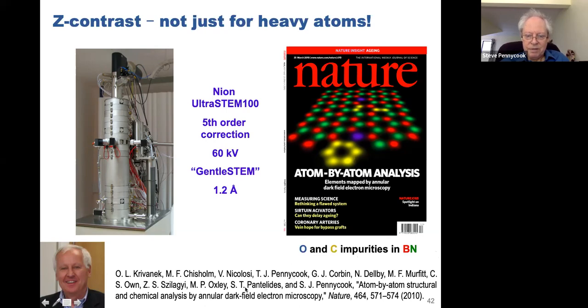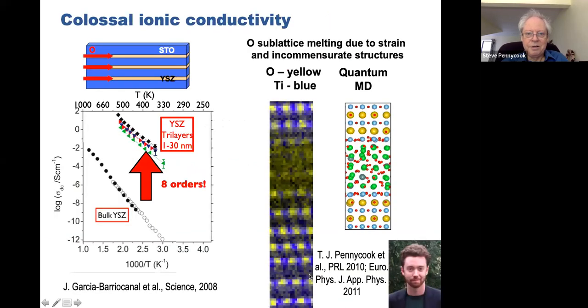And actually the guy who did this, at the same time, I said Sok Pantelides liked to send his students to the group to learn microscopy. Well, this is one of them here, someone I know pretty well. My son, Tim, was actually in the group, a student of Sok, and we set him this challenge. Previously, we saw that thin layers of YSZ, epitaxial with strontium titanate, showed this remarkably enhanced ionic conductivity. Well, Tim used quantum molecular dynamics to show that this was actually due to the oxygen sublattice melting. Because it was under this tensile strain, the lattice was expanded and there was a mismatch at the interface. It appeared that this melted.